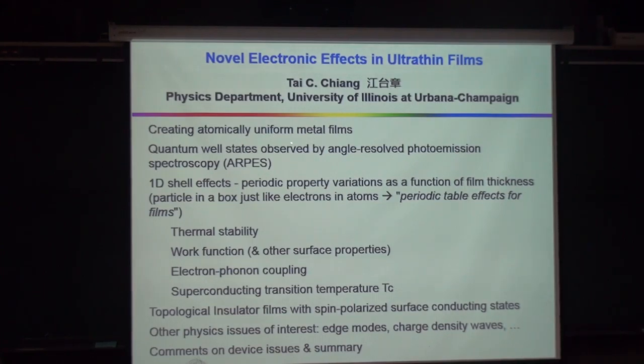Once you make those uniform films, then we apply angle-resolved photoemission spectroscopy, or ARPES, to measure the quantum well states, which you can see directly using this method. And then we discovered this 1D shell effects. So basically, as you increase the film thickness one atomic layer at a time and follow the physical property variations, you see periodic property variations as a function of film thickness. And the analogy is that we are dealing with a particle in a box because electrons are confined in the film. So it's like a particle in a box.